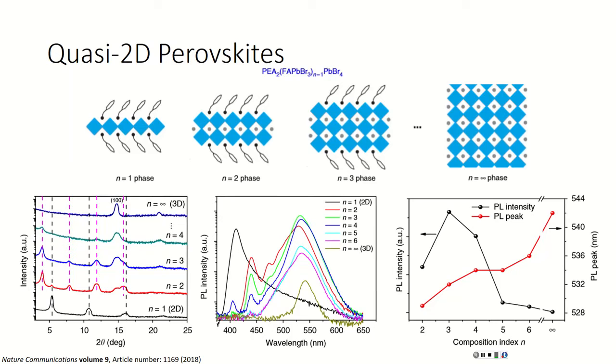But right here they have the photoluminescence chart. The key thing to this one is that N equals 3 layers. This specific one, where we have 3 layers of perovskites, happened to be the best candidate for photoluminescence. It was the one that gave us the brightest emission compared to N equals 4. N equals 2 is decent, but once again it's not the best. It's up there, but not equivalent.